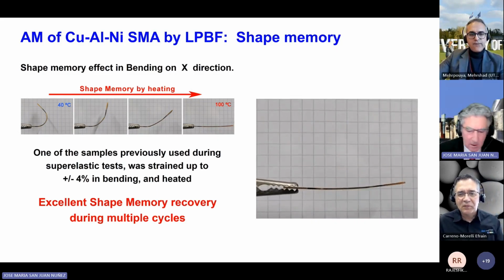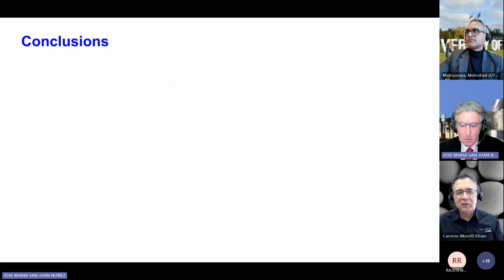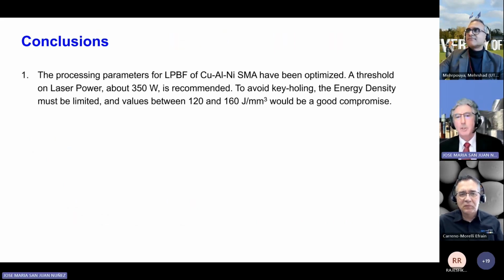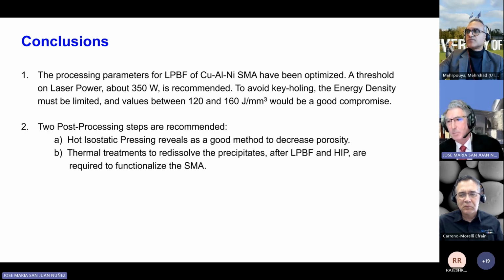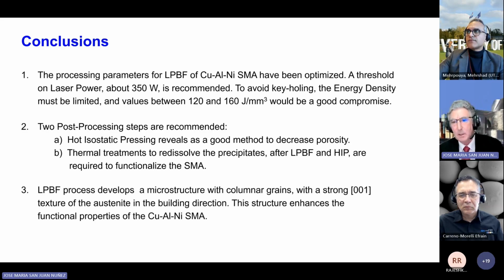So with that, let me move to the conclusions. The processing parameters for laser powder fusion of copper, aluminum, nickel shape memory alloys have been optimized. And the point is that a threshold on laser power is recommended, and the density of energy must be limited to certain values in order to avoid keyholing. Two post-processing steps are recommended. Hot isostatic pressing reveals itself as a good method to decrease porosity, like in other technologies in aeronautics.